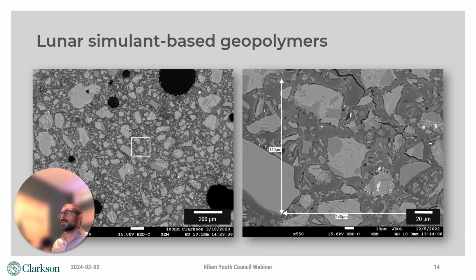One of the most interesting things we observed were the microstructures of the geopolymer samples, and here you can see an example of that. You can see a few large air voids in the image on the left, where the largest air voids are about 100 microns or 0.1 millimeters wide. But in the close-up image on the right, where the simulant particle in the middle is only about 25 microns wide, we can see that the simulant particles are joined together by a dense, continuous, and well-refined cementitious binder. Even without performing macro-scale testing, this tells us that the degree of reactivity is very high, which suggests that the material was going to be both strong and durable.